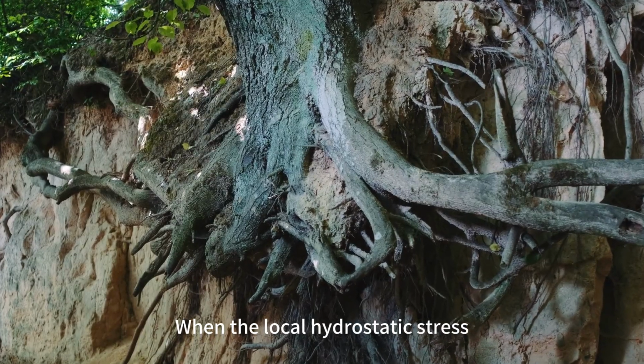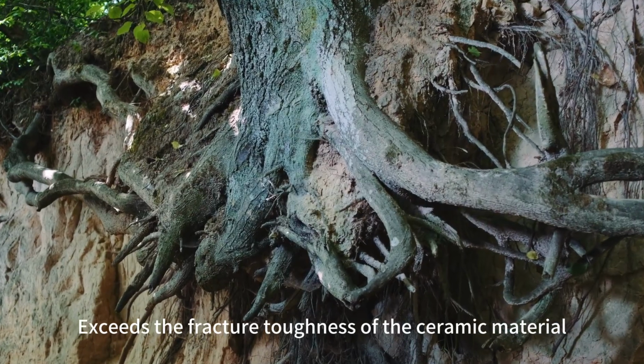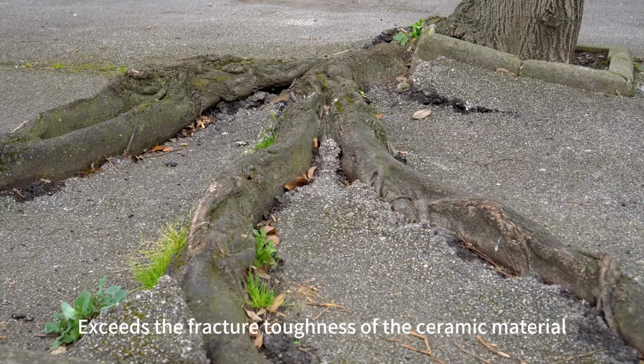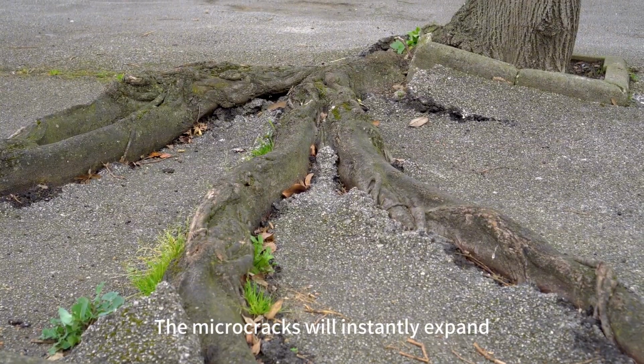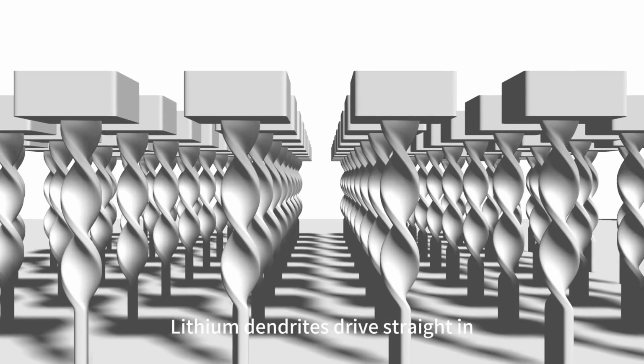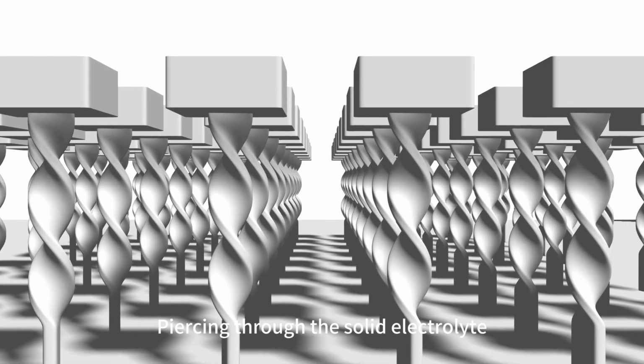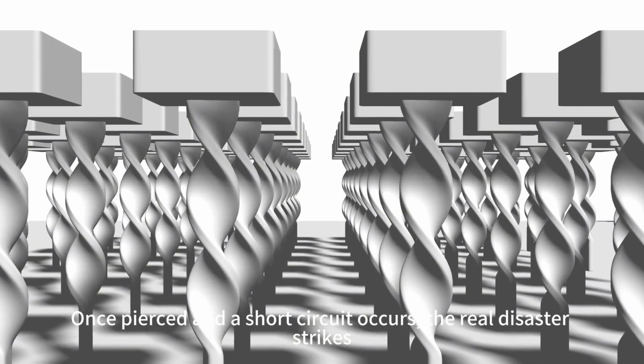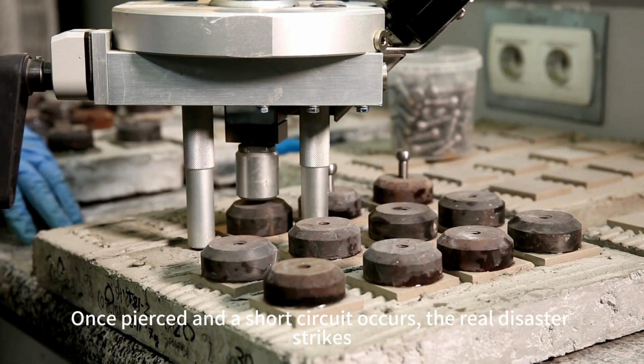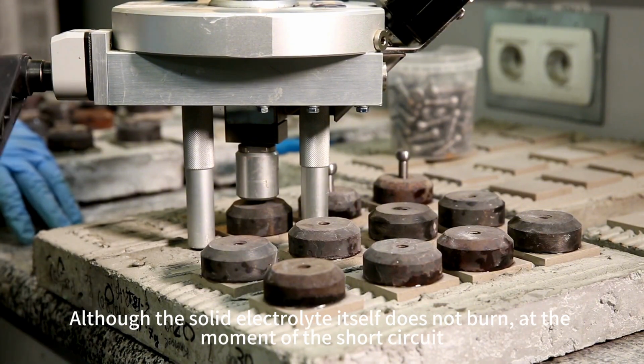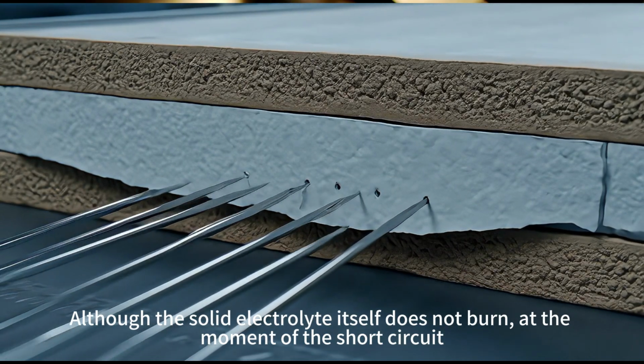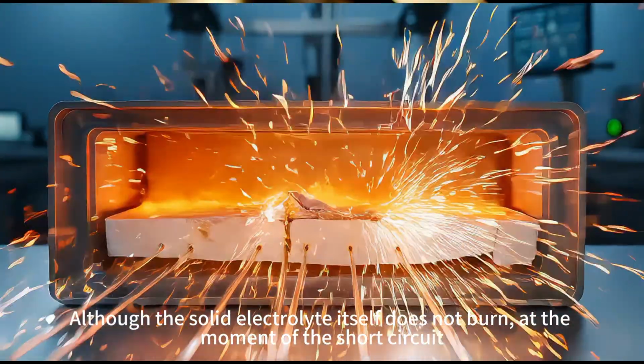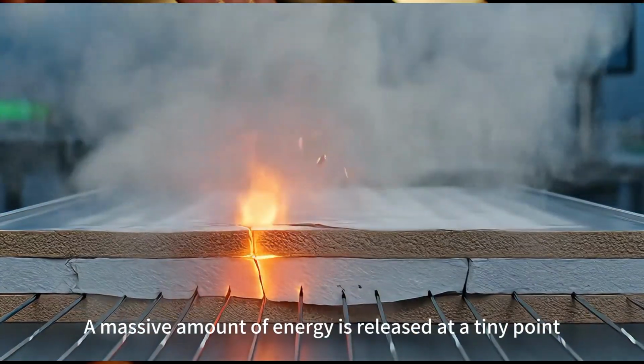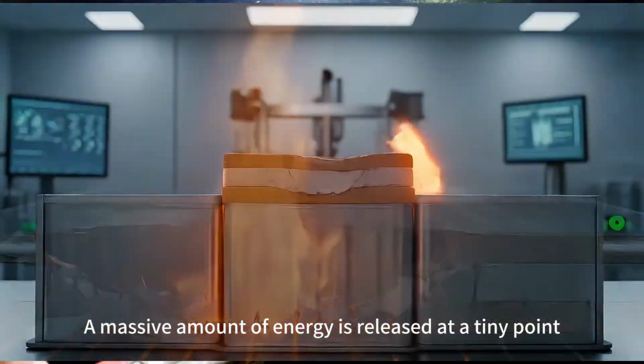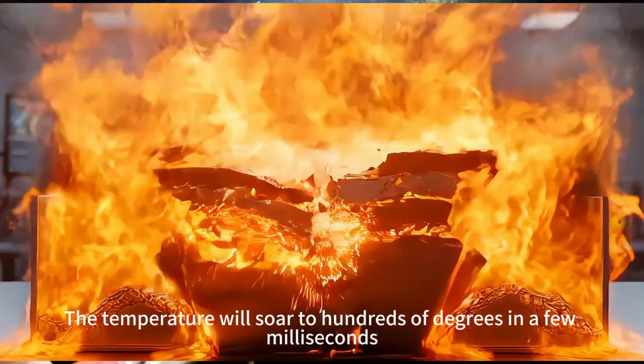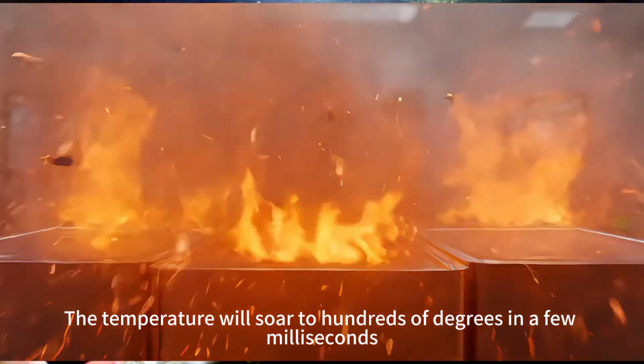When the local hydrostatic stress exceeds the fracture toughness of the ceramic material, the microcracks will instantly expand. Lithium dendrites drive straight in, piercing through the solid electrolyte. Once pierced and a short circuit occurs, the real disaster strikes. Although the solid electrolyte itself does not burn at the moment of the short circuit, a massive amount of energy is released at a tiny point. The temperature will soar to hundreds of degrees in a few milliseconds.